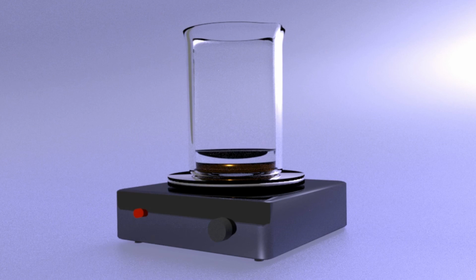Rinsing. To obtain high purity gold, rinsing is essential. When you filtered or decanted your solution, you poured off the impurities. However, your gold mud still has some solution clinging to it, and that solution has dissolved impurities in it. If your mud was dried and melted at this point, those impurities would contaminate your gold. So rinsing away those impurities is essential.